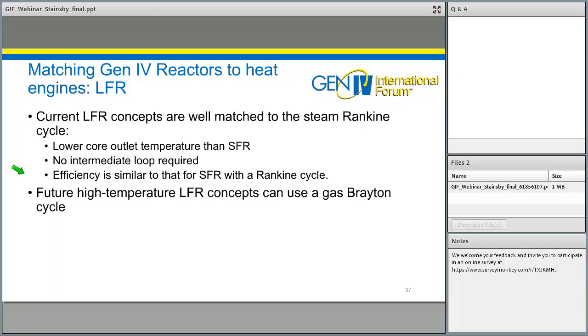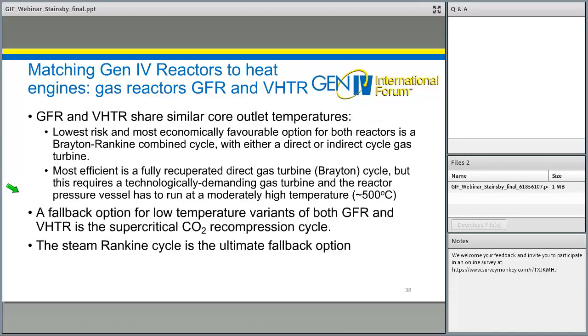And so we're looking at the sort of 40-42% thermal efficiency with LFR, even though the core outlet temperature is slightly lower than SFR. Future high temperature LFR concepts, if we're looking at things like using silicon carbide fuel cladding and structural materials, high temperature LFR, if you will, can actually use a gas Brayton cycle. Slide 38, if we look at GFR and VHTR, these both share similar core outlet temperatures. In fact, the near-term VHTRs are probably lower than what we were aiming at for VHTR.